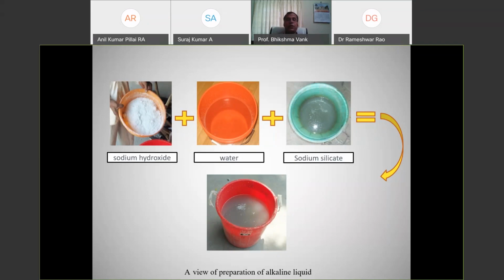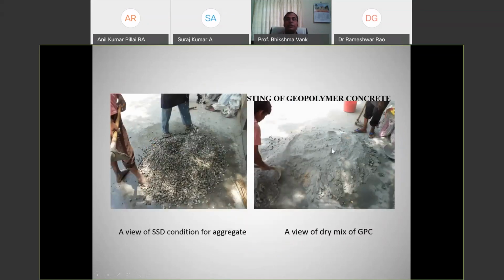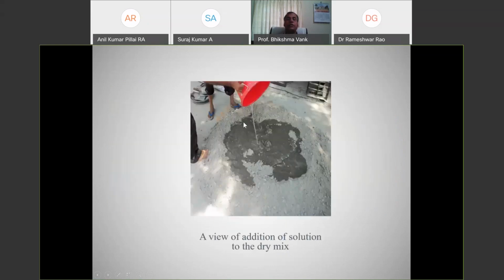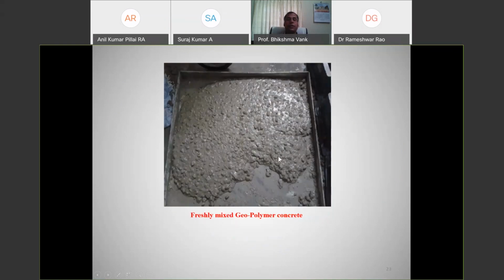your geopolymer concrete. This is how a normal mixing, fly ash, GGBS, we can use. View of the SSD condition of the aggregate, and then view of the dry mix of geopolymer concrete. We can mix like this, and then you can add the solution. View of the addition of the solution: you can add like this, and mix the concrete. So this is freshly mixed geopolymer concrete. This is very homogeneous, and you will not have any honeycomb on this, and it is very sticky, and we can make good quality special geopolymer concrete.